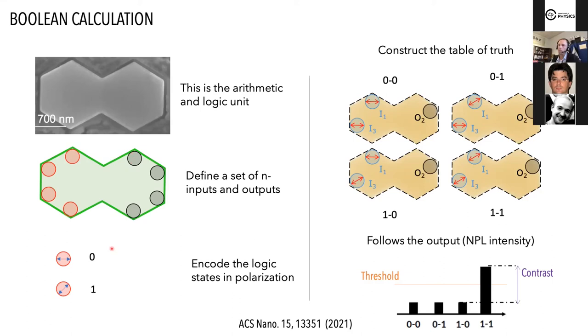our outputs. Then we are encoding the logical states, so 0 and 1, into the polarization. So for instance, in this example here, 0 would be a polarization along this direction, and the 1 would be a 45 degree tilt polarization. Then we play the game. So we are reconstructing the table of truths by sending one beam, let's say on this input, which is here, I1. Then we have another input, I3, and by changing the polarization, we can have all the table of truths. And then the output of the table will be given by this NPL intensity transported across the structure.